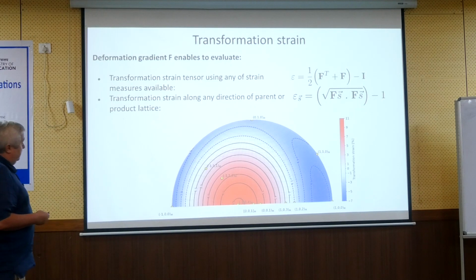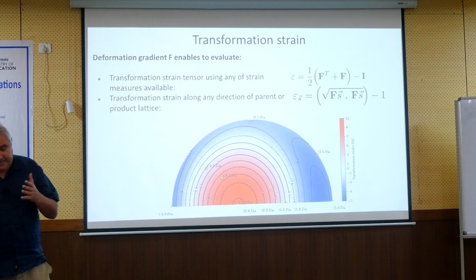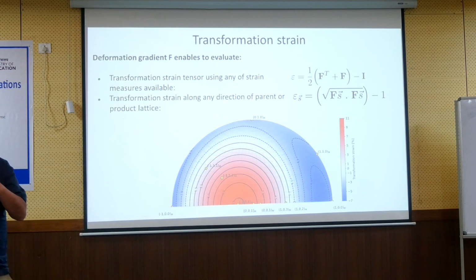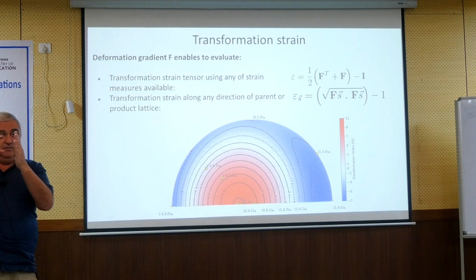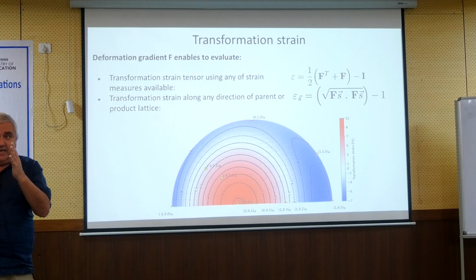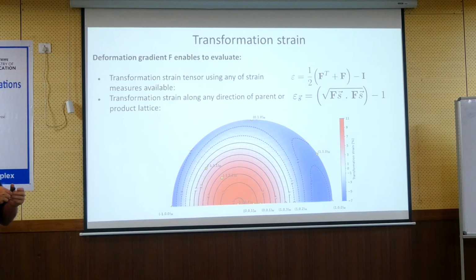And now I said that we want to come with a theory which says that in NiTinol you transfer between monoclinic, between single lattice of austenite and single lattice of martensite, which is actually such kind of transformation would be prohibited by this PTMC theory, which requires here the twin laminate. But we say instead of twinning, you have slight elastic and slight plastic deformation.